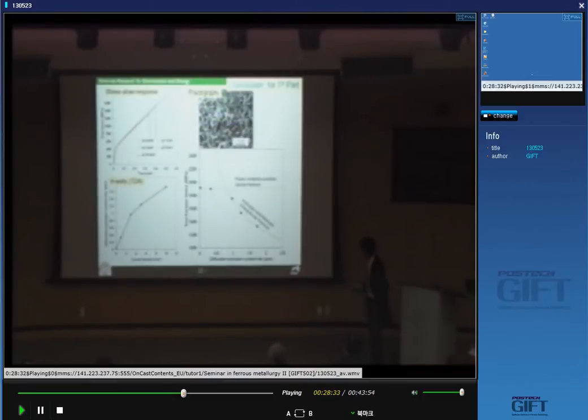Fractography showed features of intergranular fractures. If I plot the true fracture stress in relation with hydrogen entry, I can make this figure. This degradation region, fractography was intergranular fracture, which is different from ductile dimple fracture. In this condition, we observe plastic instability condition for fracture. Premature fracture due to hydrogen entry is associated with intergranular fracture.